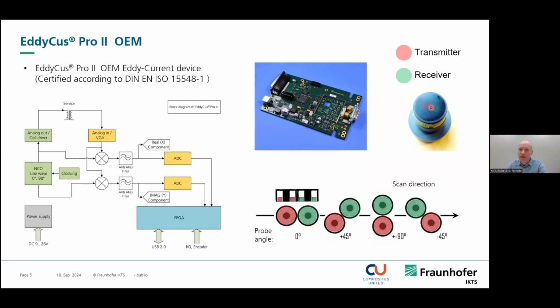Typically, we use these anisotropic probes. So we have a transmitting and receiving coil. And by rotating the probe angle, we can focus on different layers, different orientations of the sample, and can also optimize the sensitivity of our system.